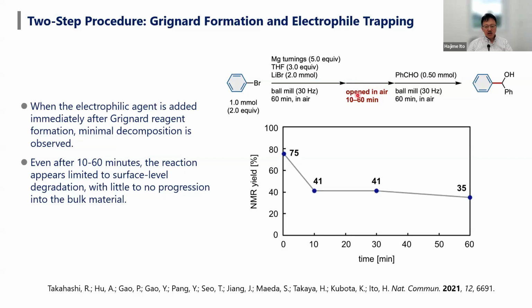Usually we just open this jar for less than 1 minute, but we tried keeping it open for 10 minutes, 30 minutes, or 60 minutes, and observed the reaction products.